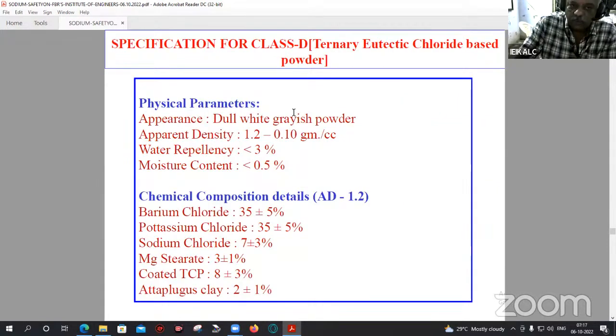And these are the physical properties or the specification for the ternary eutectic chloride based powder. It has barium chloride, potassium chloride, and sodium chloride in various ratios. And magnesium stearate is the one which improves the non-hygroscopic nature of the powder.